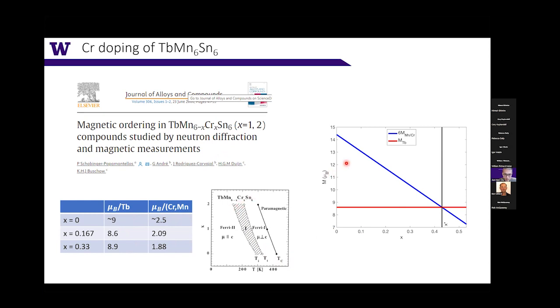So the interesting question is that in the parent compounds, you have a total of 6 manganese with 2.5 Bohr magneton per manganese. So in total you have around 14 to 15 Bohr magnetons, and that is larger than the terbium moment. So when you measure the net magnetization, it is the manganese moments that dominate the total magnetization, and the terbium moment is anti-aligned with the net magnetization. But as you reduce the average moments in the chromium and manganese layer, at some point it will become comparable to the terbium, and that's when the net magnetization vanishes. And then it will be interesting to see what kind of physical behavior you would obtain.